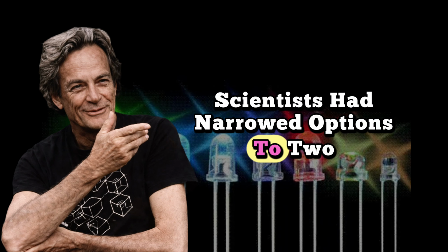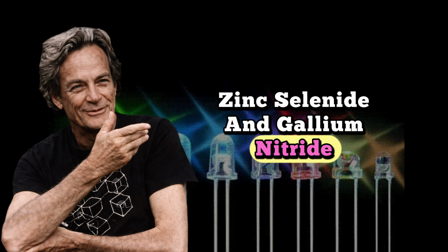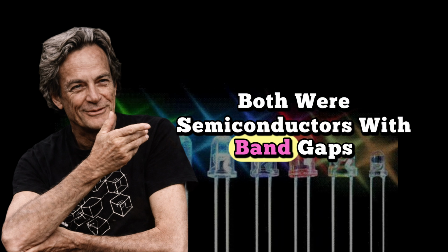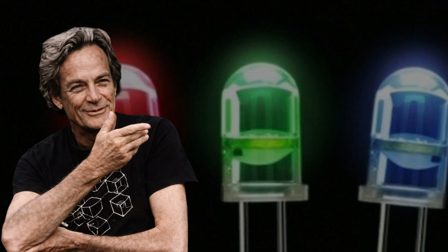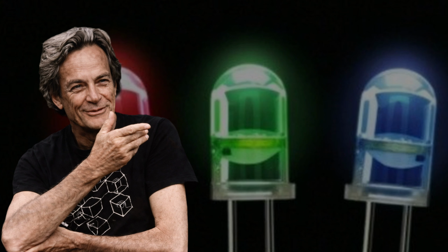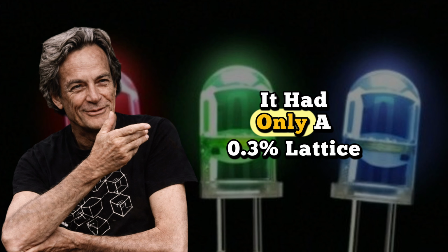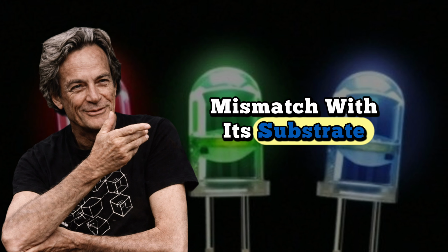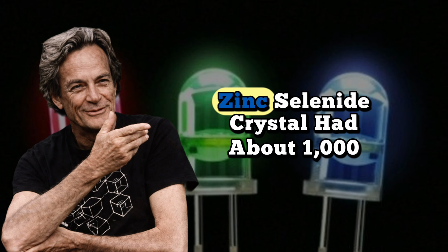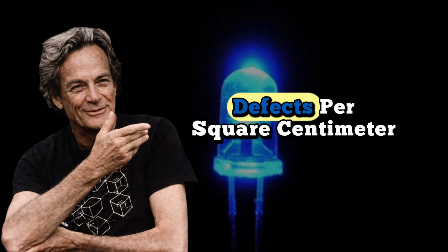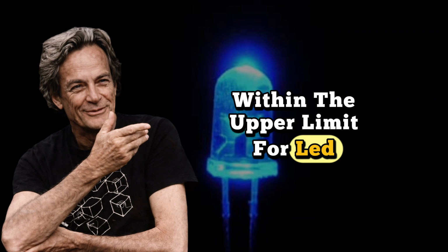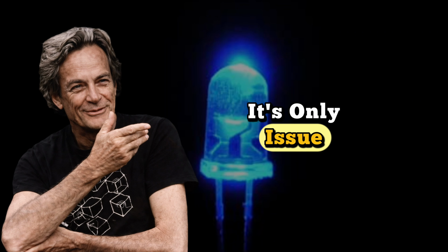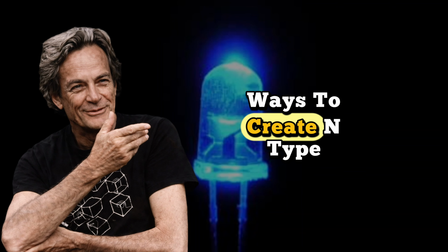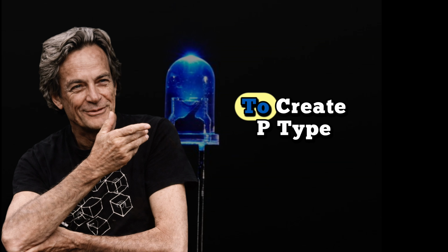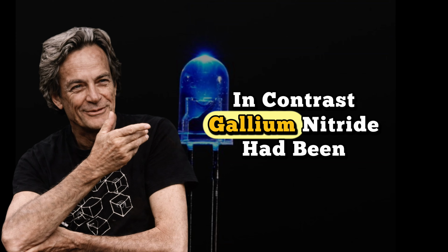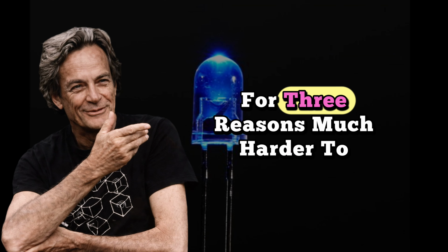Scientists had narrowed options to 2 main candidates, zinc selenide and gallium nitride. Both were semiconductors with band gaps theoretically in the blue light range. Zinc selenide was far more promising. When grown in an MOCVD reactor, it had only a 0.3% lattice mismatch with its substrate, gallium arsenide. Therefore, zinc selenide crystal had about 1,000 defects per square centimeter, within the upper limit for LED functioning. Its only issue: while scientists had figured out multiple ways to create N-type zinc selenide, no one knew how to create P-type. In contrast, gallium nitride had been abandoned by almost everybody for 3 reasons.